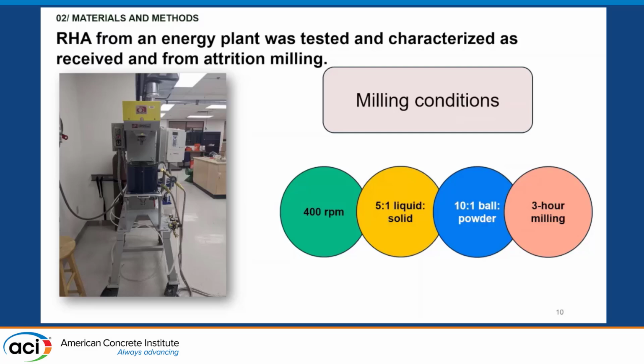It can end up in an energy plant and be used as energy, but then the next question is, what do you do with that ash from the energy plant? So we took that ash and we characterized it as received and also after attrition milling. And so these are the milling conditions that I'm working with, and as you can see here on the left, we have what our attrition mill looks like. I'm milling it at about 400 RPM with a 5-to-1 liquid to solid ratio. So there's a 5-to-1 ratio of the water to the material. And then also a 10-to-1 ball to powder ratio for about 3 hours.